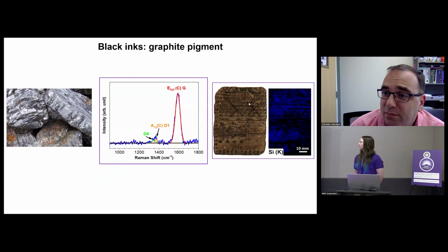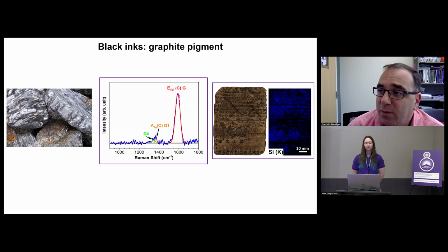It's also confirmed that this black ink contains silicon. That's also an indication of the use of natural graphite. Natural graphite is not pure. If you produce it nowadays in a chemical factory you would exclude silicon, but in the natural world you have even more impurities. We saw those. But it was pretty consistent even after that, in the 1750s. You see the same sort of pigment.